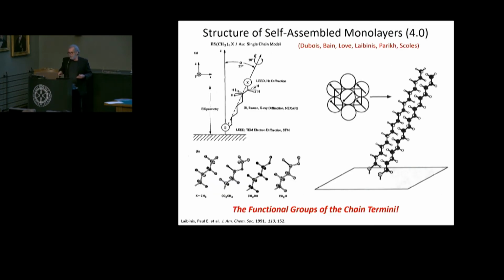But what remains is the story of the ambient functional group, because that's why we're doing this, right? And so I put the graphic that's shown in the upper left-hand quadrant. That was done by another close collaborator, Larry Du Bois, to show what these modalities were, and confirmed by even really hard measurements like helium diffraction studies, which only probe the ambient methyl interface.